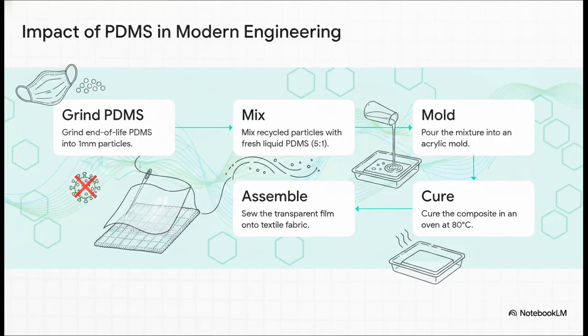This is a brilliant macro-scale application. During the pandemic, the world obviously generated mountains of medical waste. To tackle this, engineers figured out a highly sustainable life cycle for PDMS. When a device reaches the end of its life, they grind that used PDMS down into tiny 1mm specks. They take those recycled particles, mix them directly into fresh liquid PDMS at a 5:1 ratio, pour that eco-friendly mix into a mold, and cure it in an oven at 80 degrees for about 40 minutes. The resulting transparent film is then sewn directly onto fabric to create a brand new protective face mask.